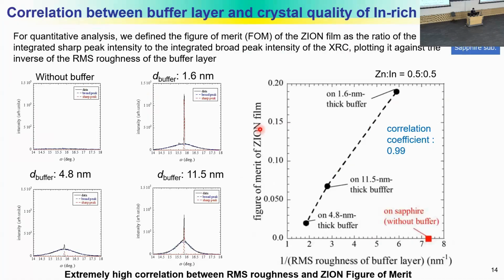So for quantitative analysis, we define the figure of merit of ZION film as the ratio of the integrated sharp peak intensity to the integrated broad peak intensity of the XRC, plotting it against the inverse of the RMS roughness of the buffer layer. The correlation coefficient is 0.99, which is very high, indicating that the small roughness of the buffer layer is important to obtain high quality ZION film.